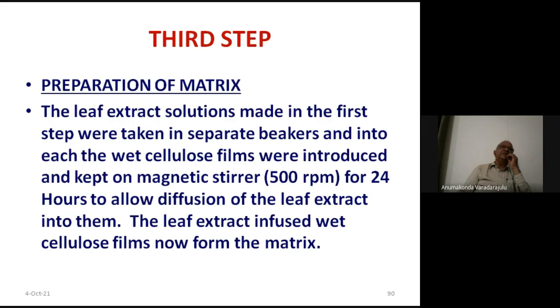In the third step, making the matrix. Actually, we made the cellulose wet film. We need not dry it. Now what we do is, we dip this wet film in this leaf extract. In the first step, we made the leaf extract. In the second step, we made the cellulose wet film. In the third step, we dip this wet film in that particular leaf extract, and then allow it on a magnetic stirrer at room temperature for 24 hours at moderate 500 RPM. And as a result, this leaf extract will be diffused into the cellulose wet film.